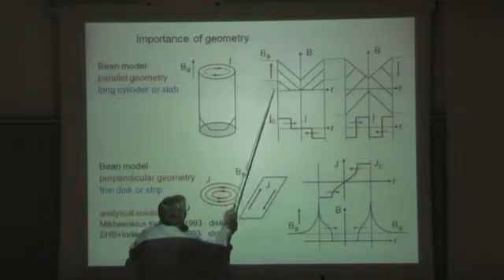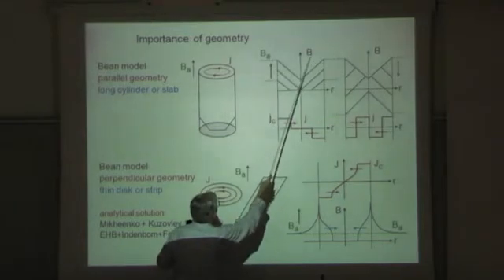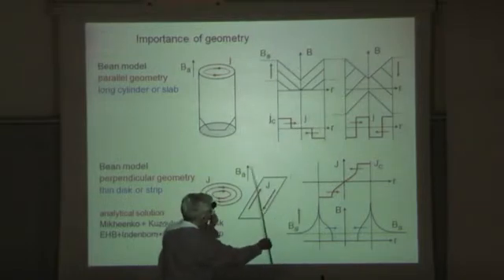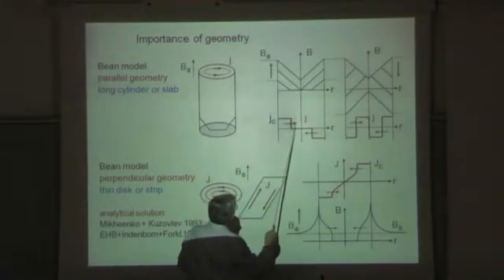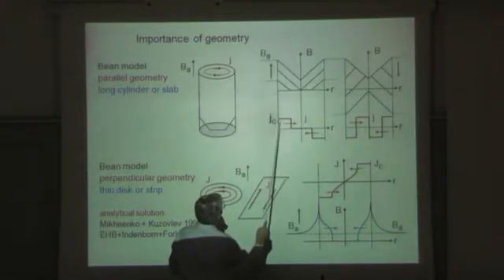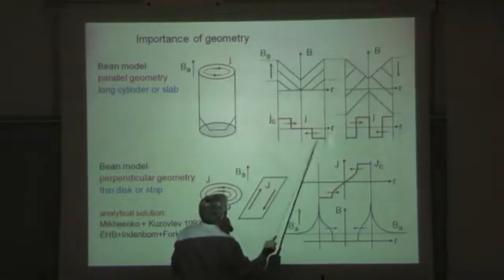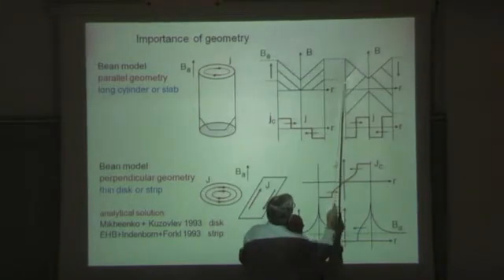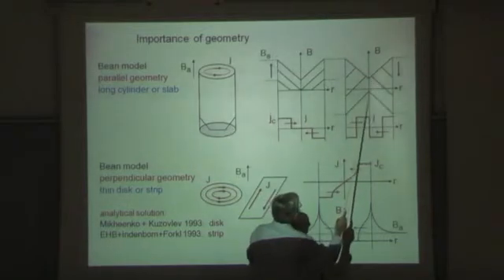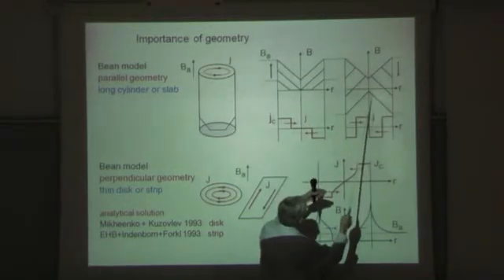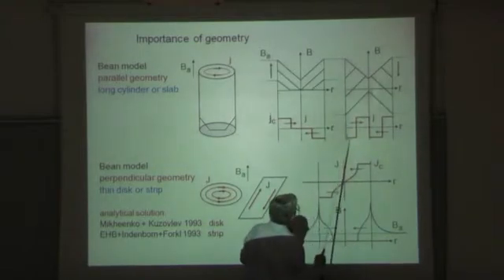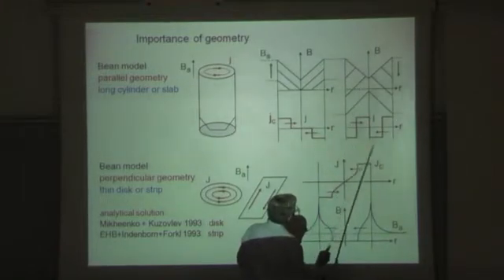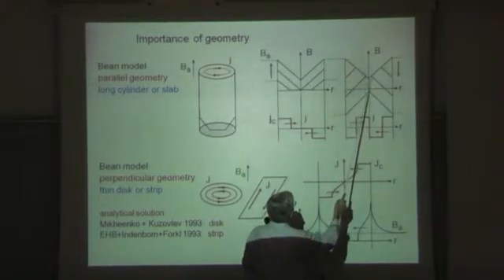And there, when you increase the field, magnetic flux, this is a flux density or induction B, penetrates linearly like a sand heap is filled. And then the current density is just the derivative of these curves. So it's either Jc or minus Jc or zero. And when you go down with the applied field, then these profiles look like this, zigzag. And finally, you have just this mountain when you are at low enough values. And the current density now is a zigzag, a stepwise constant behavior.